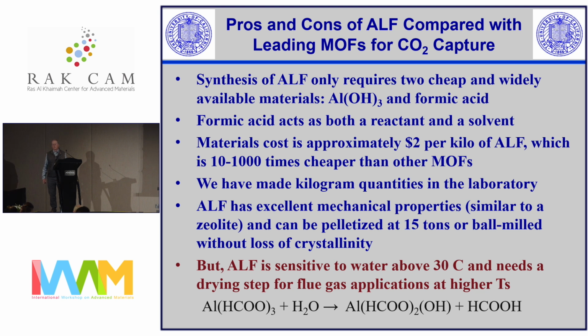So we don't have equipment for really scaling it up there, but it's easy to make, and you can make kilo quantities. The other thing about it, it's got fantastic mechanical properties. We've not measured the moduli because we've not got around to doing it, but you can calculate them very well when you know the crystal structure.